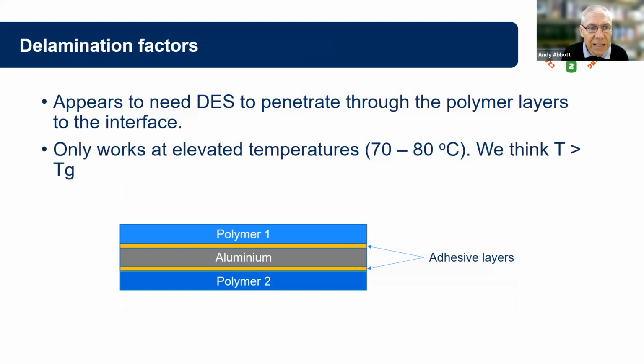What appears to happen is that the deep eutectic solvent has to go through the polymer layers or work at the interface from the edges. We found that it doesn't work particularly well at room temperature. Exactly as in the processes found in the literature, we need to go close to the glass transition temperature of the polymer, the temperature at which it goes from being a rigid polymer to a flexible polymer. So we need to open up the structure of the polymer to allow our solvent to get at those interfaces and somehow work at the adhesive layers. That's what we're trying to do with our process.